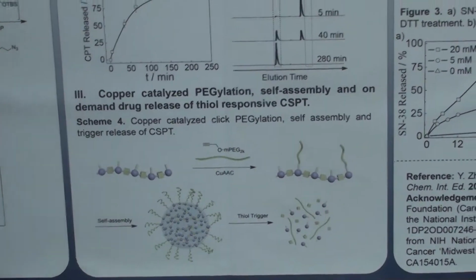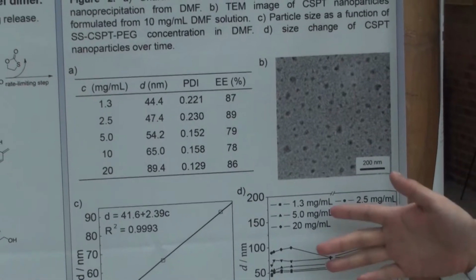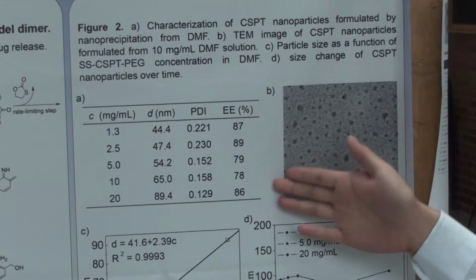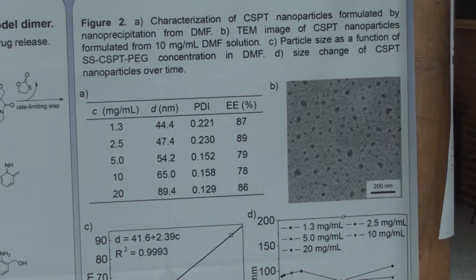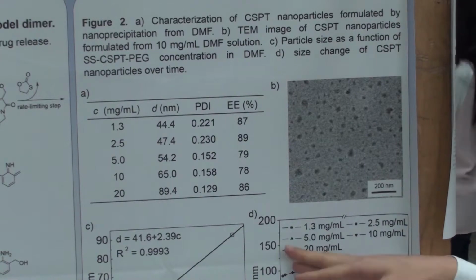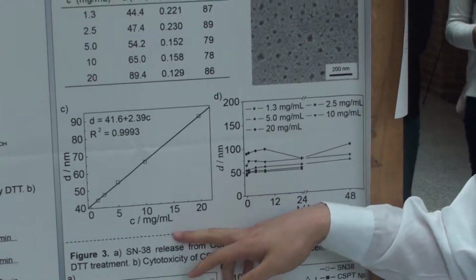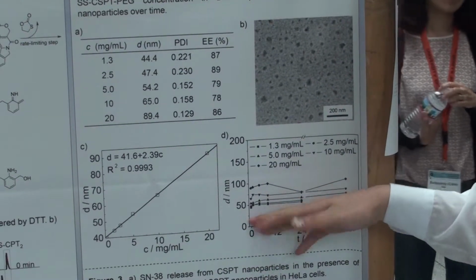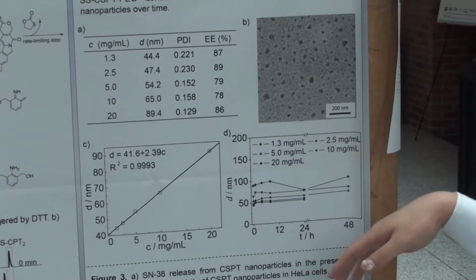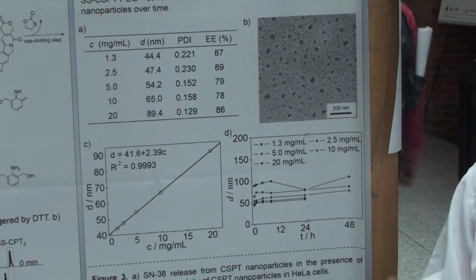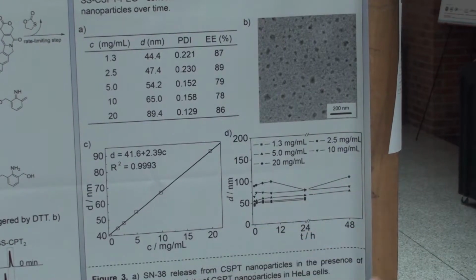Very interestingly, we find that we can easily control the size of the nanoparticles by changing the method we use to formulate it. Here we use a nanoprecipitation method. In brief, it is just dissolving the polymers in a certain organic solvent, that is DMF, and adding it into water. We found that when we change the polymer concentration in the DMF solutions, we can easily tune the size of nanoparticles from 40 nanometers to 90 nanometers. Which means that we can make a particle with designed size by simply tuning the conditions. And from the TEM, we confirm the spherical morphology of nanoparticles.